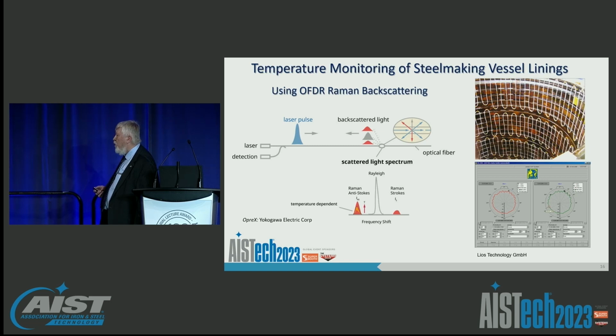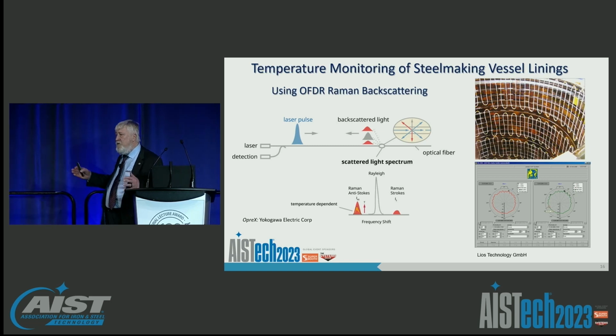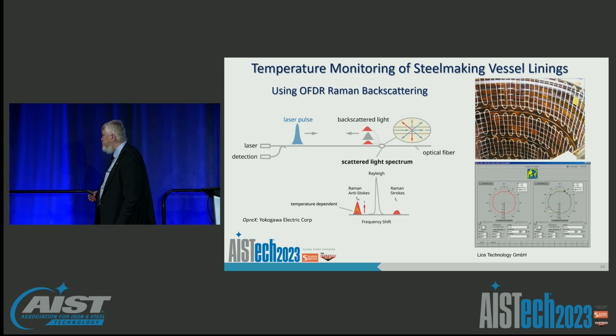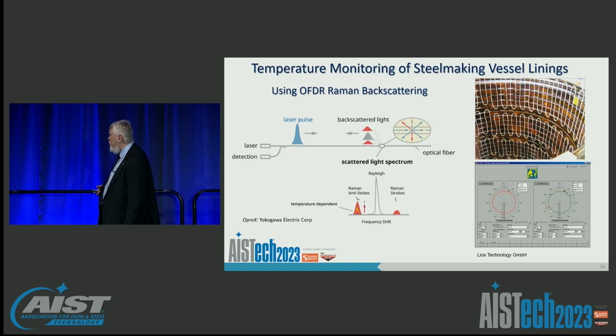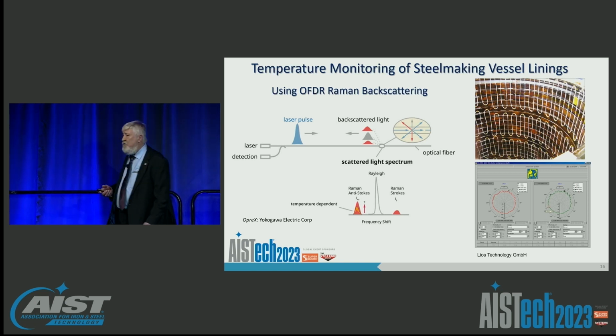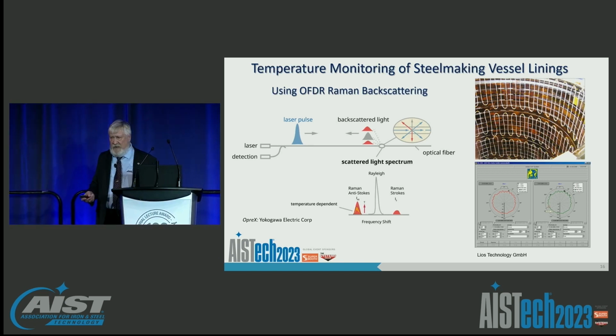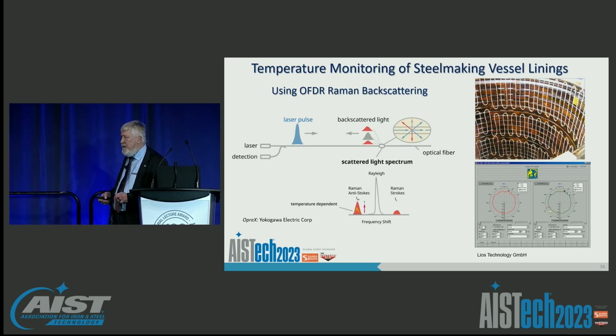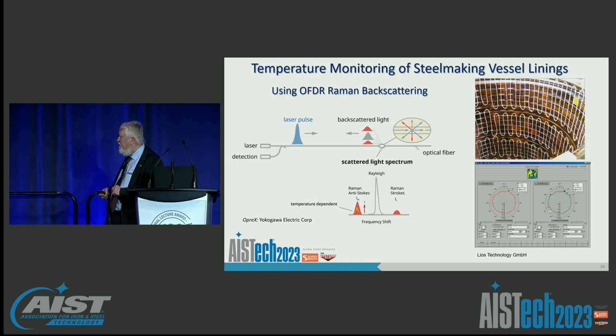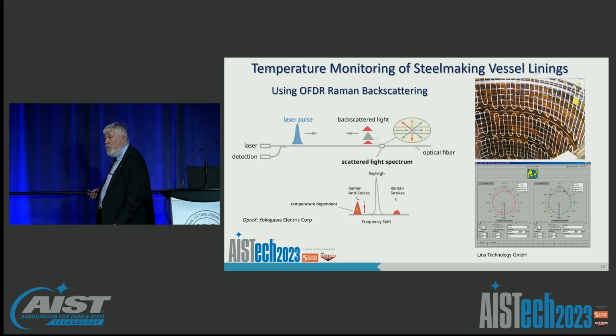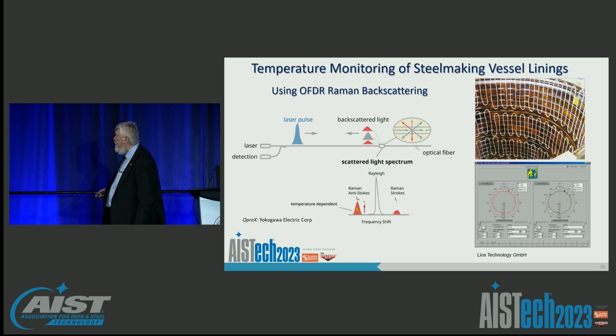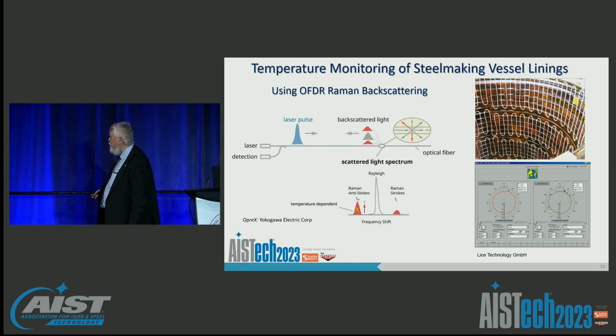There are a number of people that are marketing sensor systems to go into the refractory linings of your steelmaking vessels. And there's a couple of them that are out there that have largely settled on the use of either Brillouin or Raman backscattering, which, as you remember, is relatively low resolution. It's about a half a meter measurement length accuracy. But when put into a lining of a vessel, these things can actually still give you a lot of very good detailed information related to hot spots in the sidewalls of refractory systems. And we'll talk more about that later, but this just shows a couple of systems that are commercially available today to do these types of measurements.